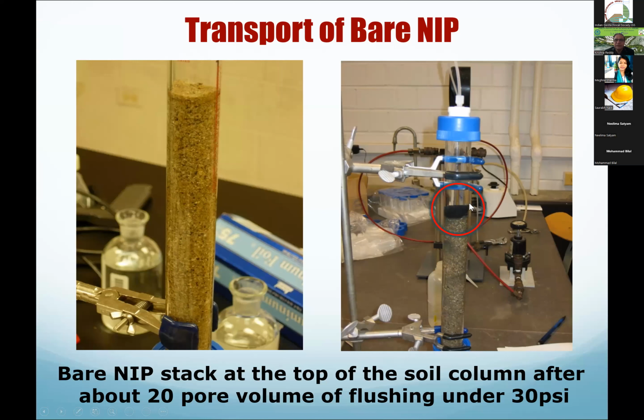But as you see here, bare nip, unmodified nano iron particles, they sit on the top of it. Nothing is moving through it. We applied 24 volumes of flushed water. We are flushing the water from the top and trying to get this one into the soil. And we even applied the pressurized condition, 30 psi pressure. We applied 30 psi pressure, 24 volumes. The water was going through it, but this iron was not going at all into the sand. If that is the case, it's useless.